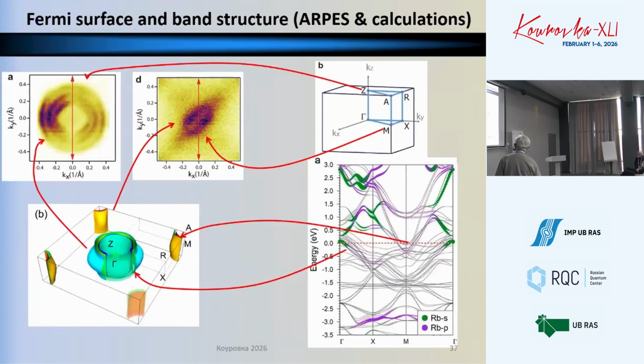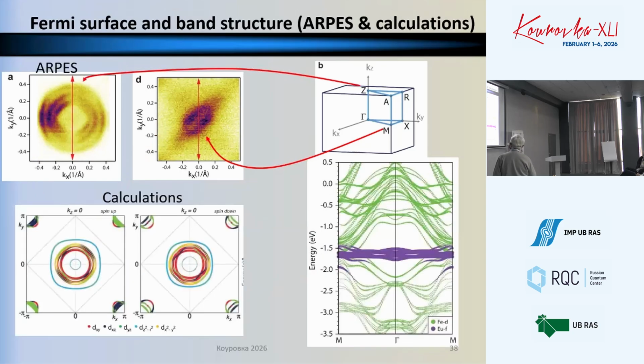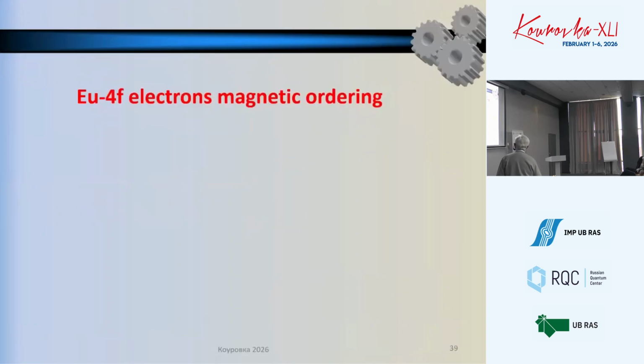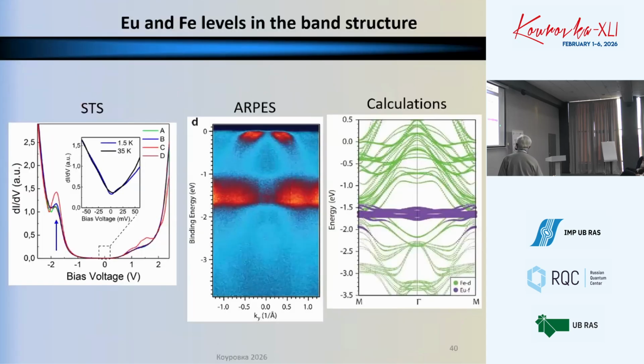Now, the band structure is typical for iron pnictides. I will not show detail. In the center of the Brillouin zone there are several hole bands, and the electron bands are at the corners. So nothing specific. What is important is to compare the levels which are responsible for magnetic ordering. They are lying far below the Fermi energy. Fermi energy is somewhere here. The magnetic layers, europium 4f electrons, are located at minus 1.8 electron volts below the Fermi energy. This corresponds to calculations.